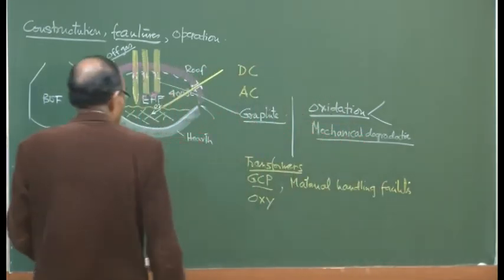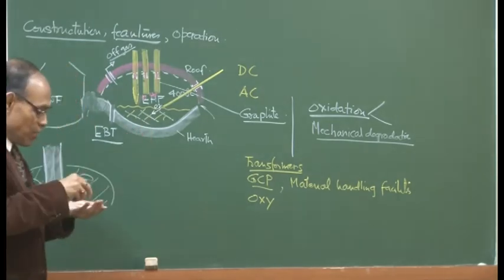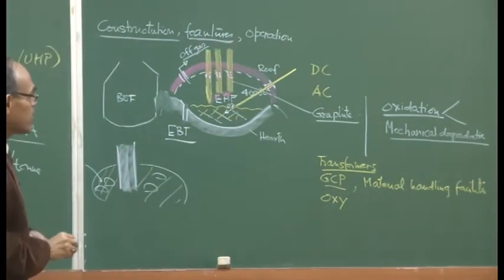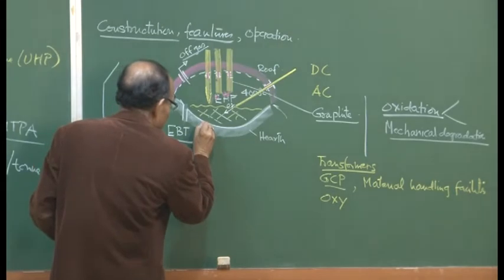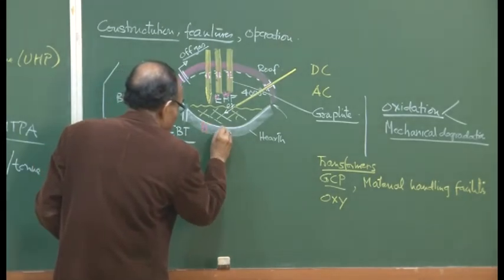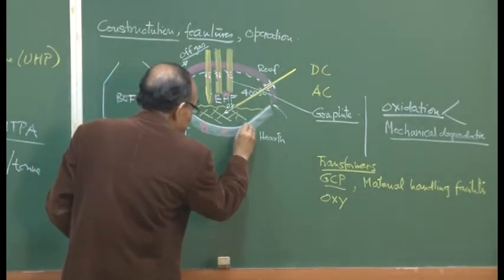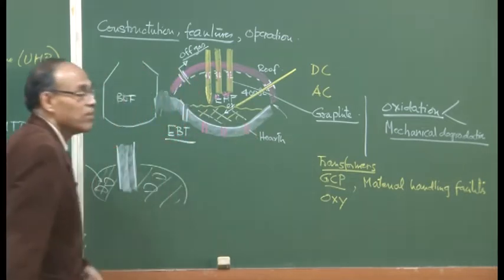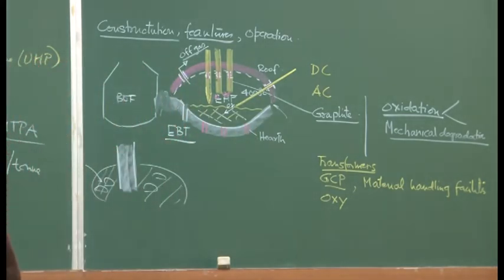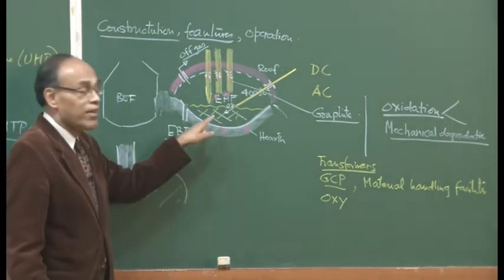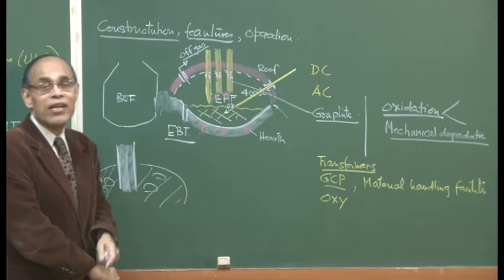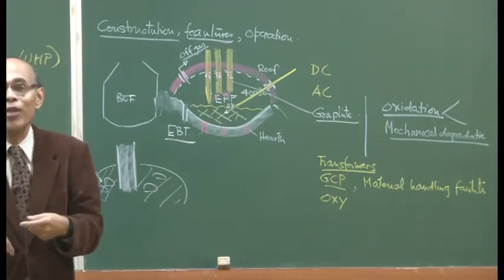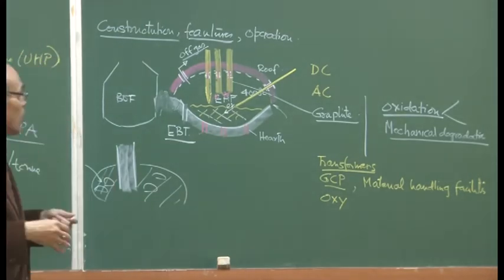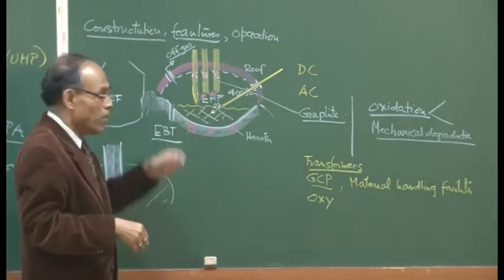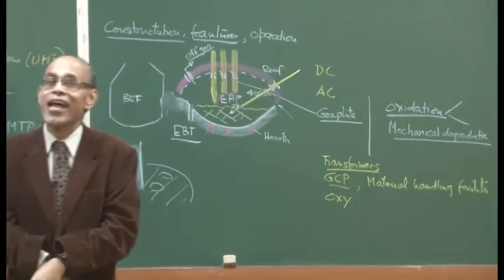Today, all the electric arc furnaces are equipped with a bottom stirring mechanism. This has been borrowed from the bath agitation process. We have seen from the bath agitation process that a little bit of argon injected through the porous plug is going to be extremely beneficial as far as bringing the system to equilibrium is concerned, as far as reducing the loss of FeO in the slag is concerned.